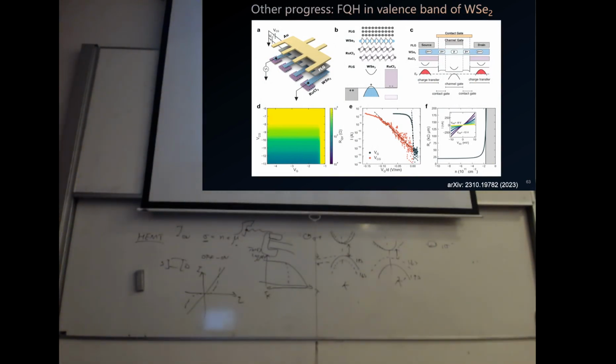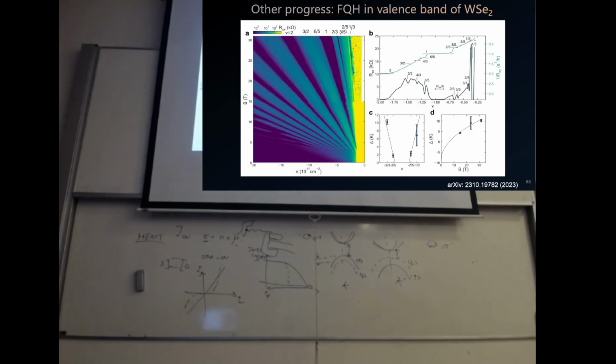For example, Cory Dean, a few months after our arXiv paper, posted another paper which measures the valence band of tungsten diselenide, which is P-type. In our case, it's N-type. What they use is another kind of contact method. They use ruthenium trichloride as a contact, which dopes the sample and the contact, and diminishes the Schottky barrier. What they saw is also something similar: 2/3, 3/5, 2/5, 1/3. So in their case, 1/3 and 2/3 are there. That's another example of the possibility of having very high mobility TMD materials.